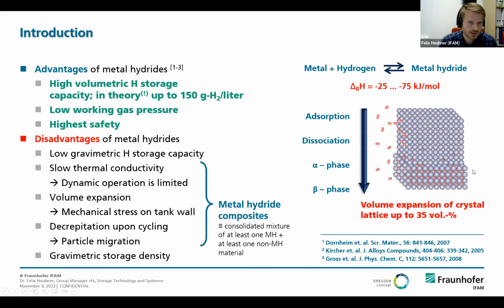To sum up the advantages of the materials, you have a very high volumetric storage capacity, in theory up to 150 gram hydrogen per liter, and a low working gas pressure at the same time. Hydrogen is bound to the materials, so you have a high safety of these materials. There are some disadvantages. Of course, you have a low gravimetric hydrogen storage capacity because you need the host material first. The thermal conductivity is often limited for metallic or powdery materials because you have small particle sizes, so dynamic operation is limited. And you have a volume expansion of the materials during hydrogen uptake.